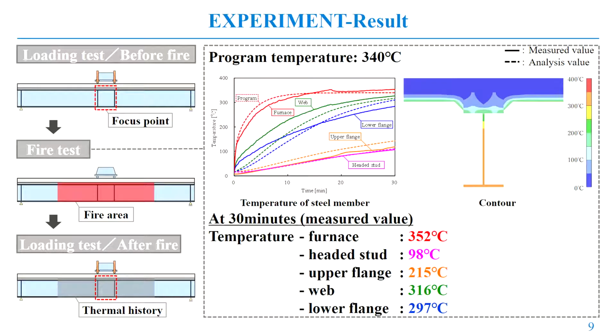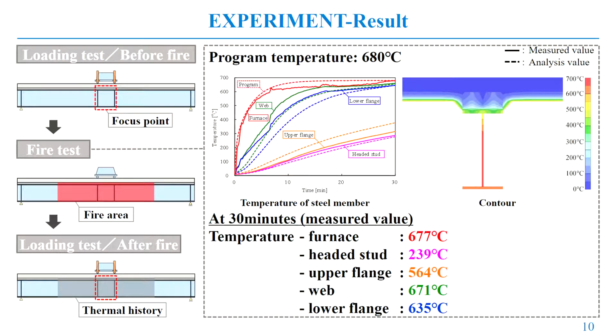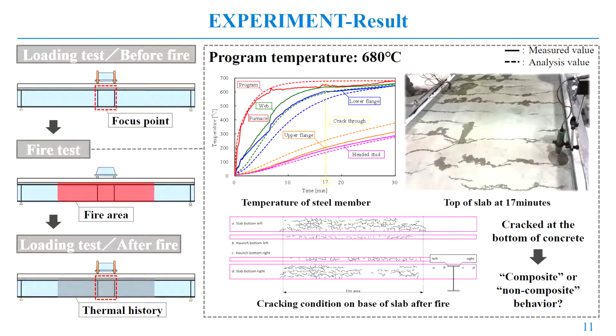These figures show the relationship between the temperature of steel member, including headed stud, and time. Also, the contour of the composite girder cross-section at 30 minutes. This figure shows at 680 degrees Celsius. The analytical value of the steel member were almost the same as the measured value. Also, through cracks formed at 17 minutes, and this picture illustrates cracking condition on top of slab.